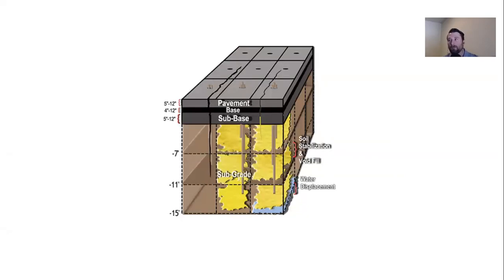So with cementitious grouting, you're trying to create bulbs. We're trying to create zones of influence. And because our material starts out as a liquid, it's going to travel the path of least resistance and then expand and push loose material into more dense material. And as those confining pressures start to give you uplift or bump at the surface,